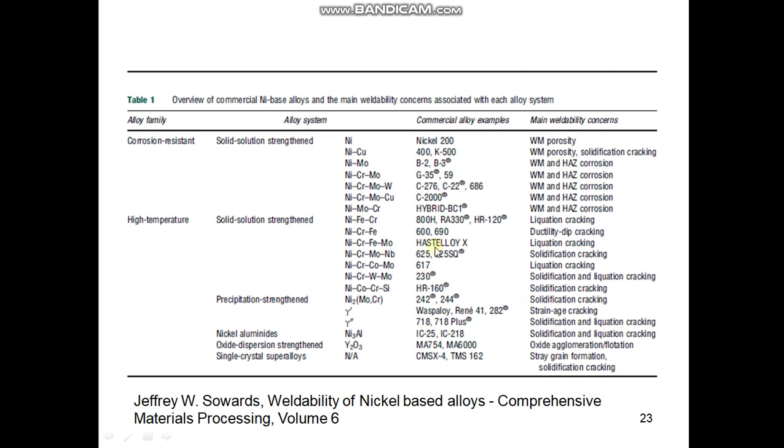Then Hastelloy X has liquation cracking issues, and precipitation hardened materials like Waspaloy suffer from strain age cracking. There is also mention of some advanced materials or alloy systems like nickel aluminide, oxide dispersion strengthened and single crystal superalloys. They also have some challenges and weldability concerns. So this is a very good table for looking up information about the weldability of nickel based alloys.